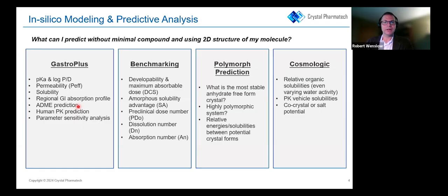So the benchmarking we'll be talking about, again, is amorphous solubility and preclinical dose number, dissolution number. And from a polymorph prediction standpoint, what is your most stable crystal form? Very early on, with say 10, 15 milligrams of material, you can grow a single crystal. Having that crystal structure, we can then lean on that in the polymorph prediction and get an understanding of where we are in the polymorph landscape. So the form that we are making currently, is that close to the lowest energy? Is it the lowest energy?